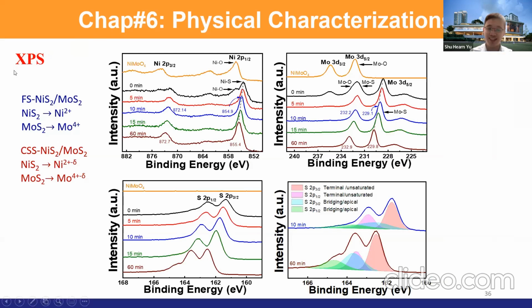So we performed XPS, and we see that as we control the temperature and the time, 0 minutes, 5 minutes, 10 minutes, 15 minutes, and 60 minutes, you can see the shift of the nickel peak, the shift of the molybdenum peak, and the shift of the sulfur peak as well. So if you know how to do XPS fitting, then according to the literature, you can identify different types of terminal sulfur: terminal unsaturated sulfur or bridging apical sulfur.